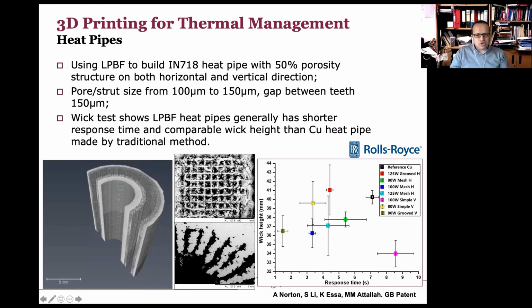Instead, what we tried to do was that we basically printed them using SLM. We generated a structure with a very high surface area, as you can see on those teeth you see in front of you. Each one of them is around 100 microns, let's say, and in terms of their height, around 1 millimeter in height, and they surround the shape.